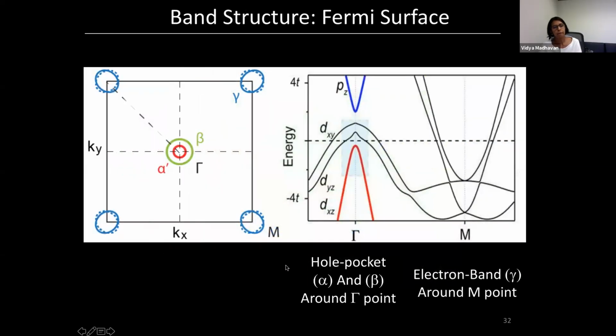Just for the experts, the band structure of this material looks like this. This is the Fermi surface. You have multiple pockets crossing the Fermi surface, and there are these two pockets at the gamma point, and then there's the pocket at the M point. The reason to show you this is to tell you that each of these pockets that crosses the Fermi energy should actually give rise to its own superconducting gap. So when we measure the superconducting gap with STM, we might see 1, 2, 3 gaps coexisting at any given location.